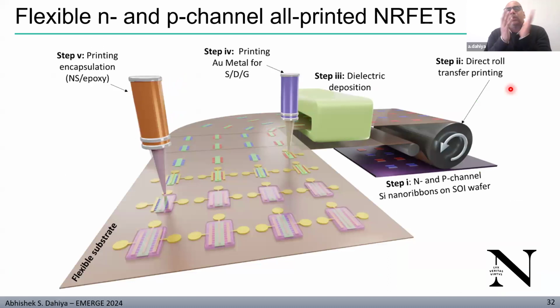In the previous example, we used a conventional, lithography-based approach to fabricate source, drain, and gate, and we are trying to avoid lithography even during the fabrication. So what we have done in this study is that we have used a drop-on-demand printer. It's an electro-hydrodynamic based printer, which can ideally print a 1 micrometer line, from SIJ company.